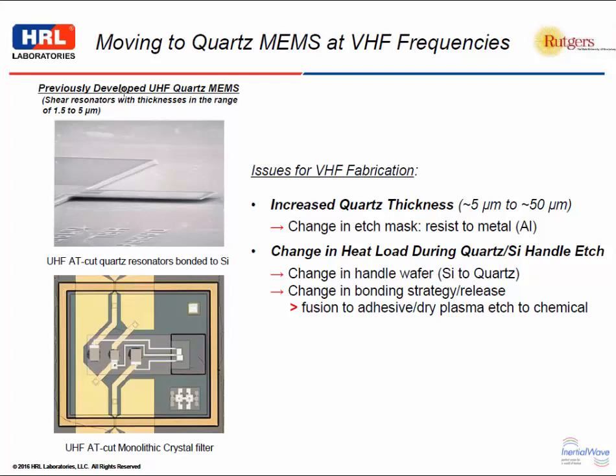But how do we get to a more stable SC cut ovenized design requiring VHF operation? Well, we have to increase the quartz thickness from the several micron range to, say, 50 microns or above. And that required us changing the mask for doing the quartz etching from resist to an aluminum metal mask. And more importantly, the heat load, which may not be obvious initially, during the quartz etching and the silicon handle wafer etching that we were using became a big problem. Wafers cracked like crazy, and our yield went to zero with that process. So we couldn't use this process to make a VHF part.